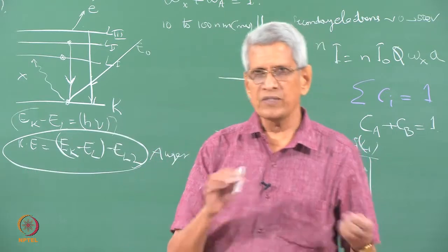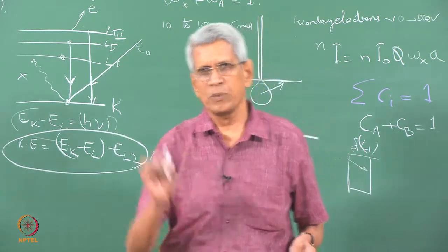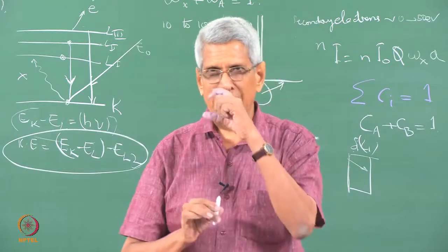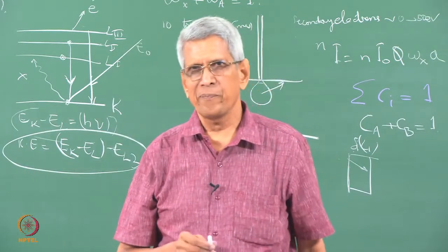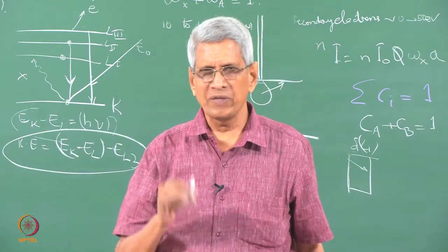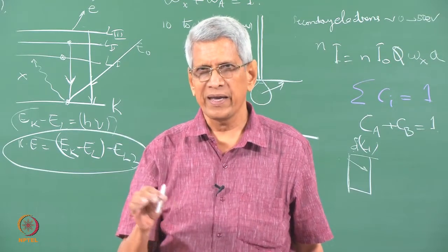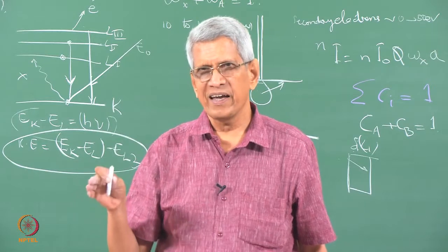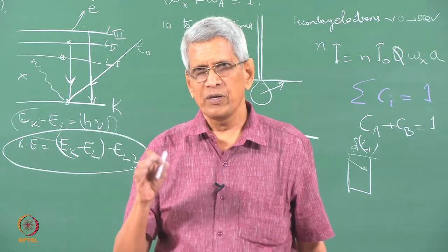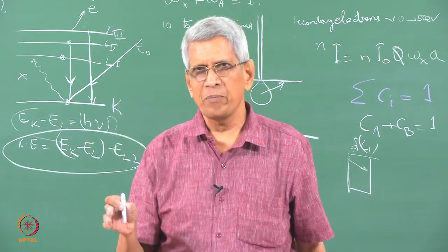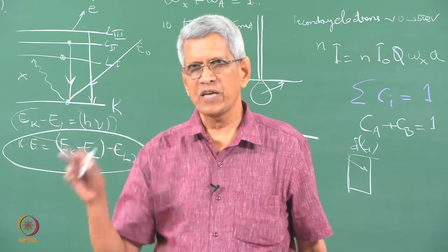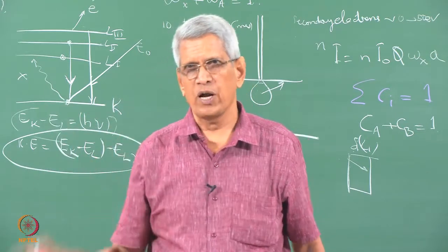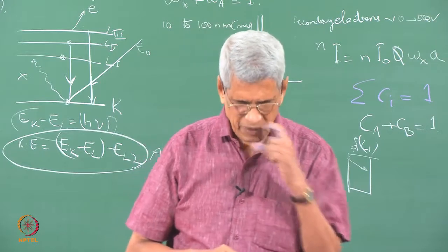Then there is what is called coherent bremsstrahlung, especially on a crystalline material, when the beam is arranged specifically along the zone axis and then enters. Bremsstrahlung is radiation which is being produced. Because of the coherency of the beam, this can give rise to some peaks appearing at different energies on the overall background. That is one process which can take place.